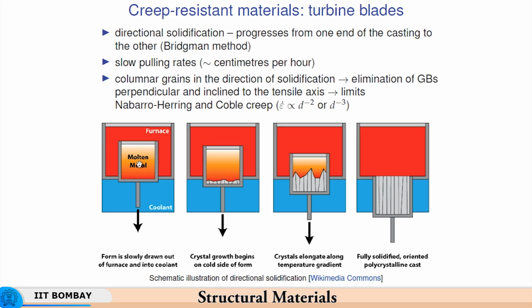So, part of this form is in the coolant, part of it is in the furnace. So, as you slowly withdraw this part, you have solidification taking place on this surface, and the direction of growth of the grains will initially be in the direction of temperature gradient, and as you withdraw the form progressively the temperature gradient will be consistently set up in the vertical direction, and then you get columnar grains. So, fully solidified and oriented polycrystalline cast grains are obtained, but this is still not a single crystal.